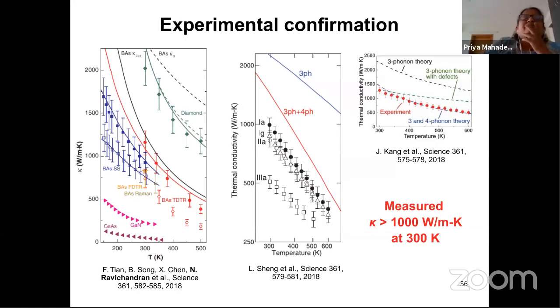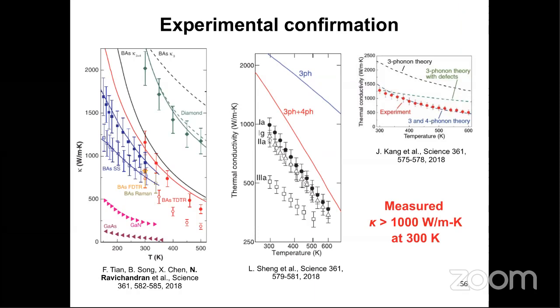So I just wanted to mention here that even though 4-phonon scattering is having such a large effect on the thermal conductivity of boron arsenide, the measured value in all 3 works is still exceeding 1000 watt per meter Kelvin. To give you some perspective, silicon's thermal conductivity is only about 150 watt per meter Kelvin at room temperature. So this is about a 6-fold increase. There's also independent work which shows that boron arsenide has similar electronic properties to that of silicon. So now you have a material which is as good an electronic material as silicon, but 6 times a better heat conductor. So you can really envision passively cooled electronic materials with boron arsenide.